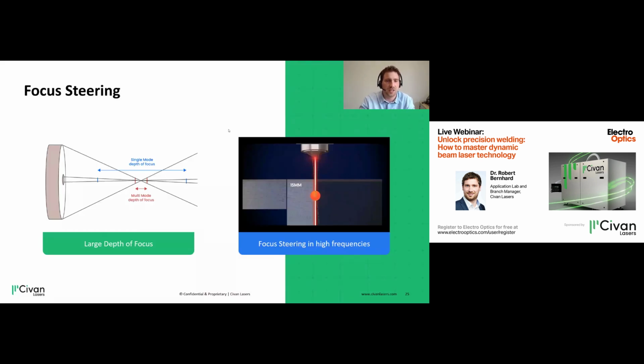Now to the final thing I want to get about our laser. The beam works in 2D. We are also able to do 3D beam shaping. And we have a single mode laser, which already means that we have a very long focal distance, but also we are able to do the focus shifting using our electro-optical coherent beam combining. And the focus steering in these frequencies really helps to get the best results in deep penetration welding, but also working on lower depth, so we can adjust A for the workpiece and B for the things the material itself needs.